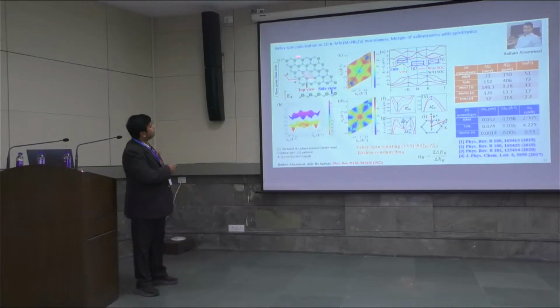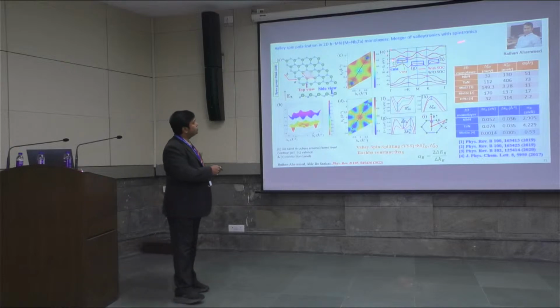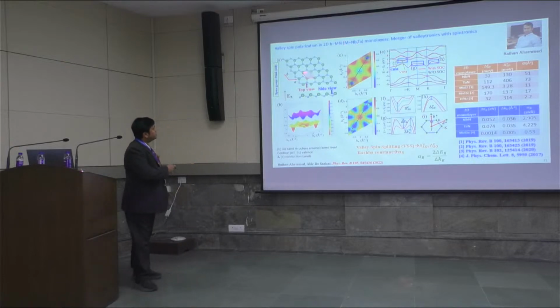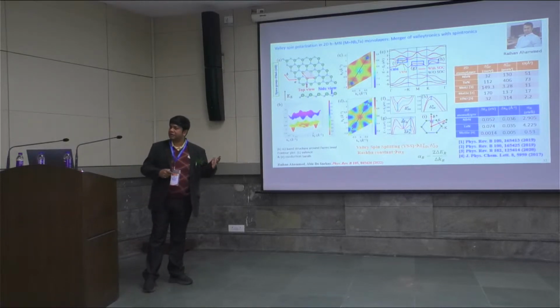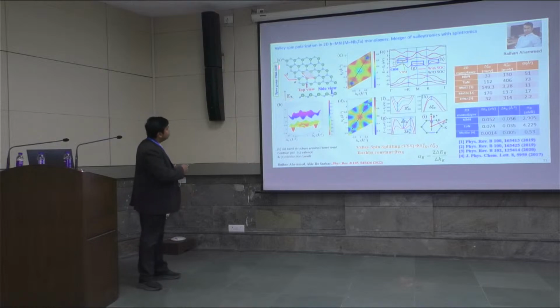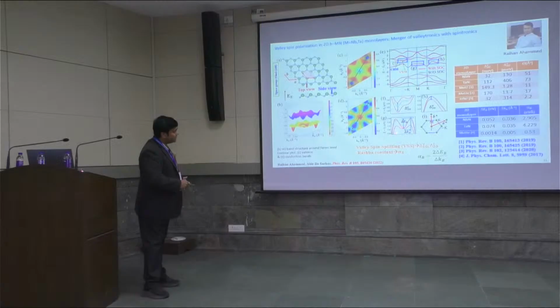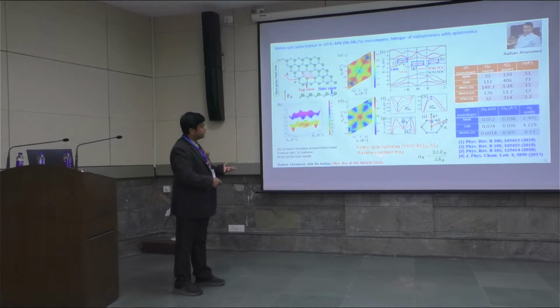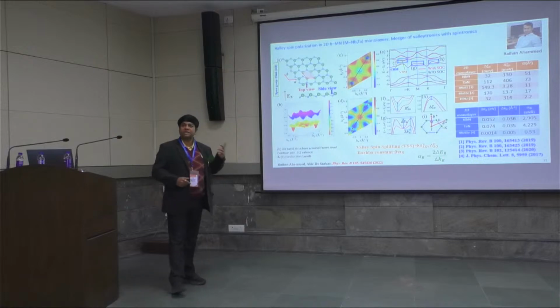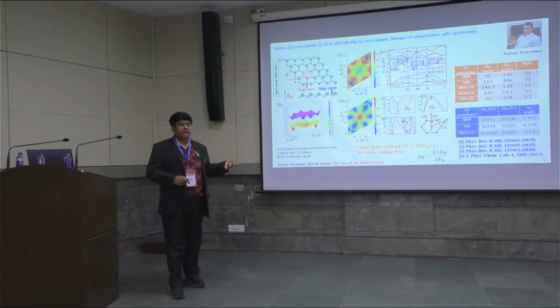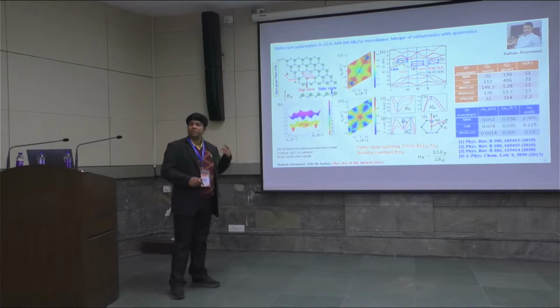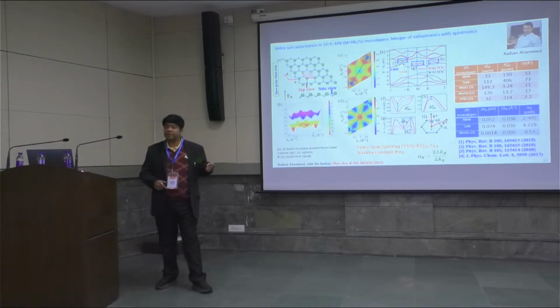Then moving on, we have also proposed these monolayers for the integration of valleytronics with spintronics. This niobium nitride monolayer or tantalum nitride monolayer, they have a hexagonal honeycomb lattice and a polar buckled structure. Because of the polar buckled structure, an out of plane electric field intrinsically arises in it, which induces momentum dependent spin splitting, and that gives rise to a Rashba constant. The Rashba constant is quantified by this parameter, and the higher the Rashba constant, the better it is for spintronics application. So a material which has a high Rashba constant is suitable for applications in spintronics where spin degrees of freedom are utilized.